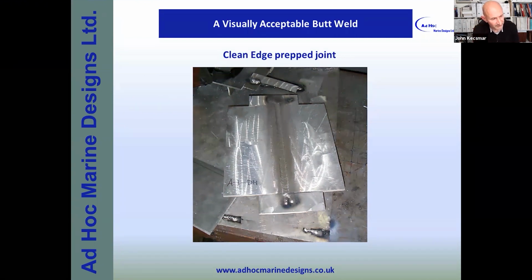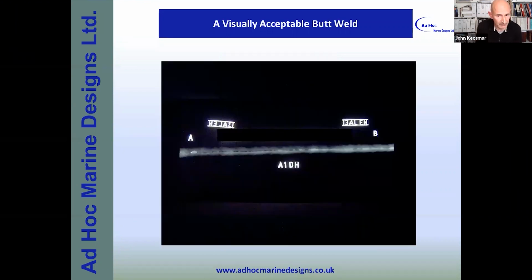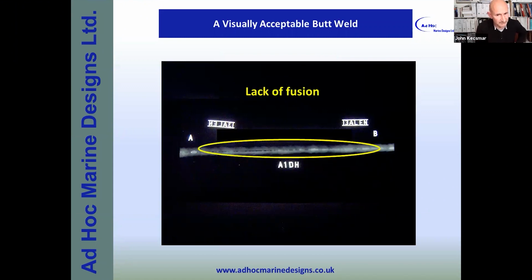Some time ago, when I started doing my PhD, I conducted a series of experiments. I wanted to see the effect of the quality of the weld on fatigue life. So I prepared a whole series of joints, and this one in particular is a standard clean edge prep joint. All the welder had to do was just weld it using his skill. And visually, this is an acceptable butt weld. And here is the X-ray. As you can see, there is an extensive lack of fusion. So it failed the X-ray.